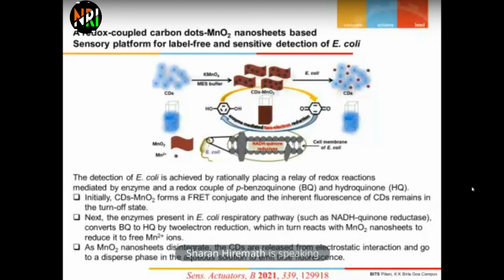These MnO2 nanosheets after reduction will become Mn2+, and the sheet nature of the MnO2 will break, and the fluorescence of the carbon dots will be released into the solution to give back the fluorescence. Initially the CDs and MnO2, due to the FRET, the fluorescence has been quenched.